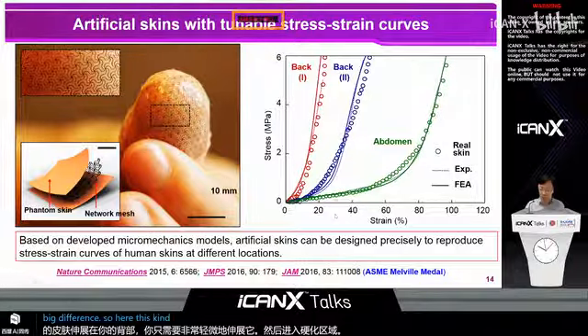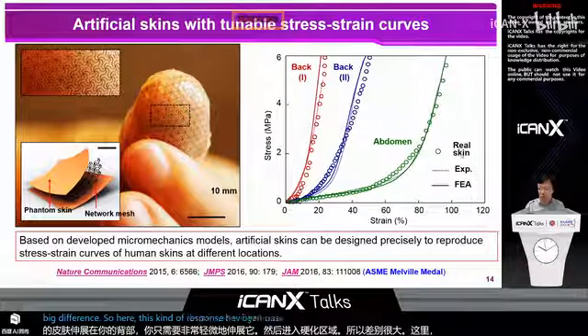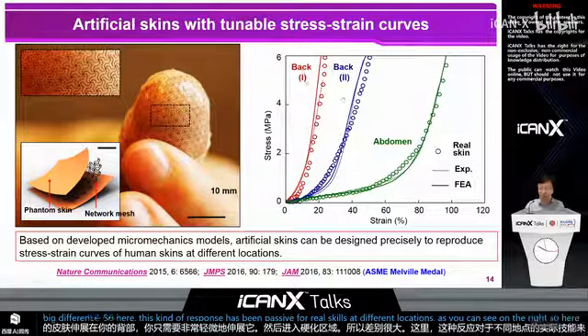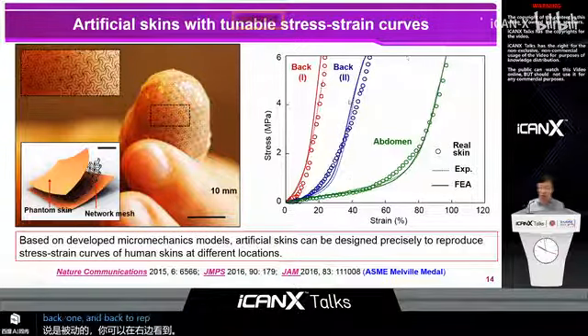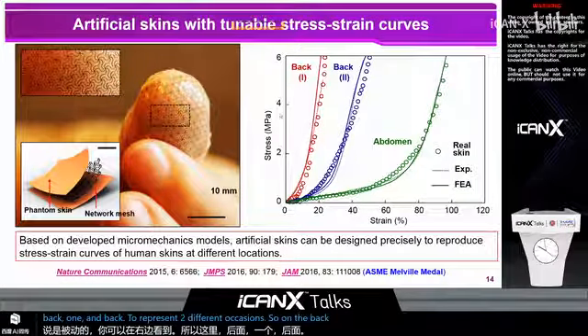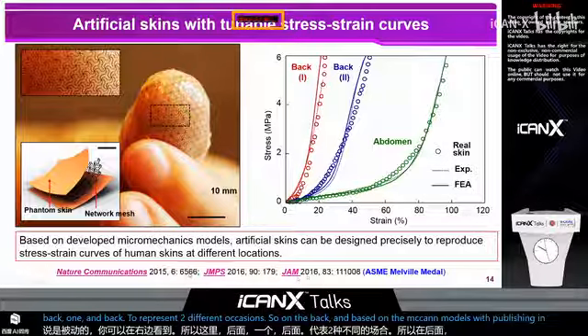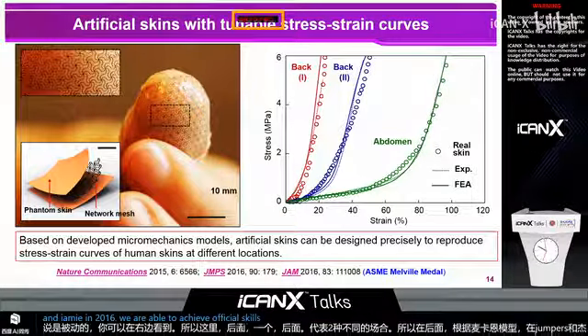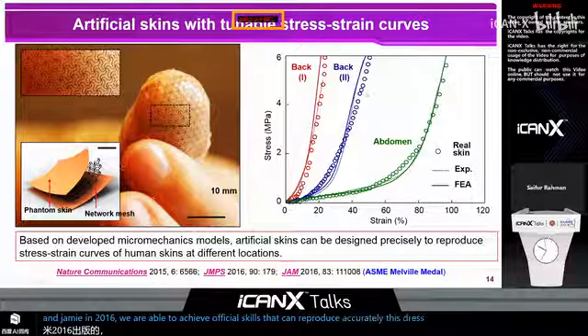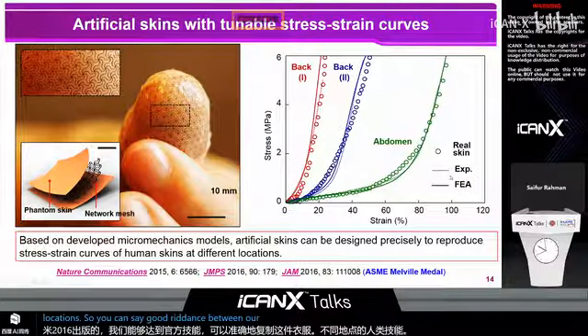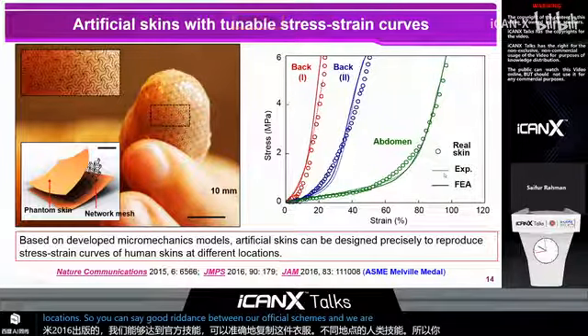So here, this kind of mechanical response has been tested for real skins at different locations, as you can see on the right. Here, back 1 and back 2 represent two different locations on the back. And based on the mechanics models we published in JMPS and JAM in 2016, we are able to achieve artificial skins that can reproduce accurately the stress-strain curves of human skins at different locations. So you can see good agreement between our artificial skins and real skins. Okay.